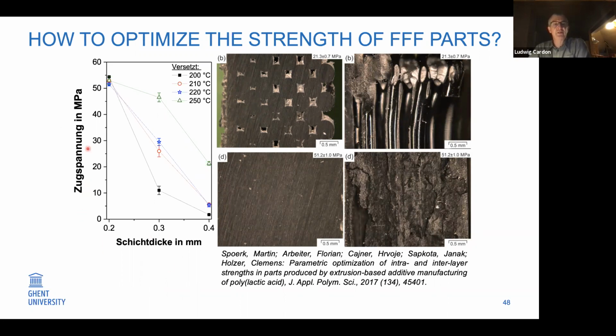So you see there is a high tensile strength when we have a very thin layer thickness of the 3D printing. But when we increase the layer thickness, the tensile strength will reduce a lot, taking into account our processing temperature. So what we investigate in this case is the effect of the processing temperature of the 3D printing combined with the layer thickness to see how we can improve that. And that's what you see here.